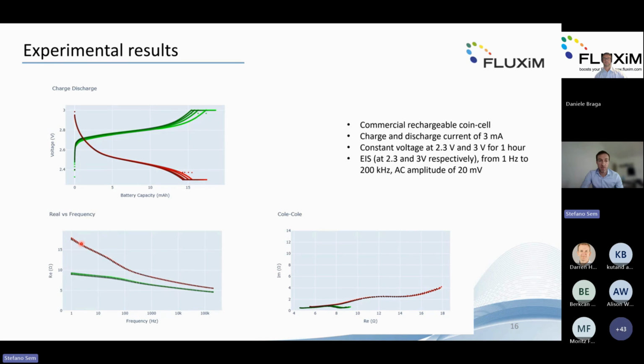Here there is an impedance measurement at the end of every charge or discharge step. So we have 4 impedance measurements after the discharge and 4 after the charge. Here is the real part of the impedance versus frequency. Here is a Cole plot. And this was done on a